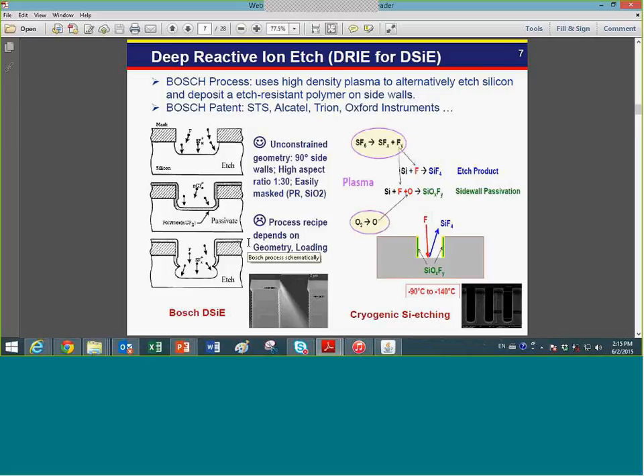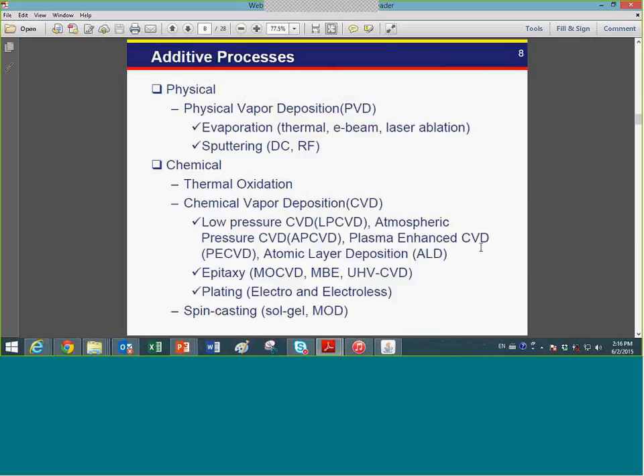Instead of etching the material at a regular temperature range near 0 degrees Celsius, we can cool the substrate down to less than minus 100 degrees Celsius to give you a really smooth sidewall, so you can still do deeper silicon etching. You can also control the profile of the sidewall through a compound such as a polymer. This polymer is interesting: once the temperature of the substrate rises to a certain temperature, it evaporates, so there is nothing built up at the sidewall. Now let's move on to adding materials on top of each other. The additive processes involve physical or chemical processes.